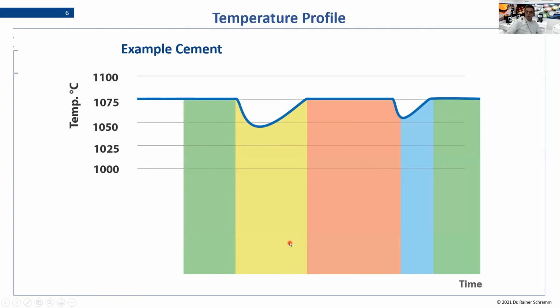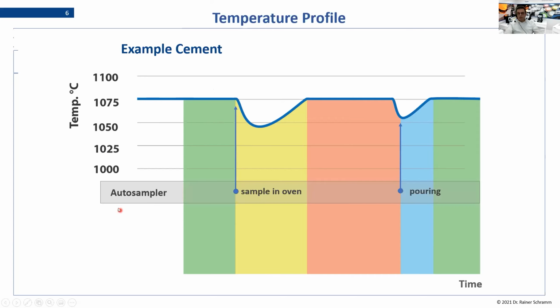But let's have a deeper look into our temperature, because that is, in my opinion, one of the most important parameters. And I would like to give you an example. Cement, perhaps 1 to 10, 1 to 8 diluted. You can fuse this, for example, at 1075 degrees. The moment the autosampler introduces a sample, the temperature will drop because you open the furnace. You introduce your sample, you close your furnace, and then, of course, the temperature is going up again. It's stabilized. Then for pouring, you have to open it again, same situation.